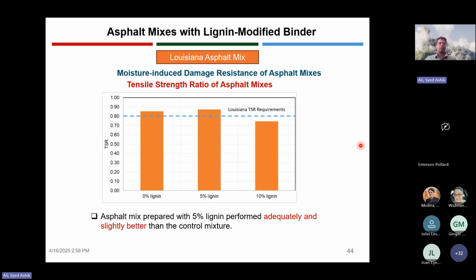Tensile strength ratio of asphalt mixes. We have seen significant improvement of the tensile strength with the addition of 5% lignin. But with 10% lignin, the TSR value went down a little bit. So we can expect that the 5% lignin performed pretty adequately and slightly better than the control mix. This is one of the positive things that we have seen with the addition of lignin.